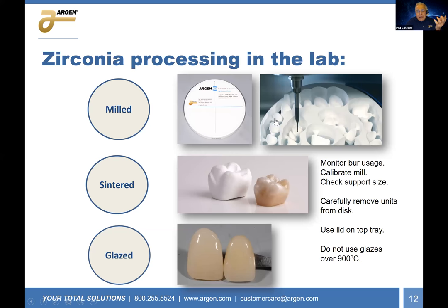However, they have to be very careful in how they process their zirconia. For example, we say here, monitor the burr use. Well, if you're making a long span bridge with zirconia, and they don't allow for the change out of the tools, which by the way are really expensive, that long span bridge may not fit, and that's a problem, right? Because you have to redo the entire thing. So a little bit of care on the dental laboratory side is necessary for any part of the process.